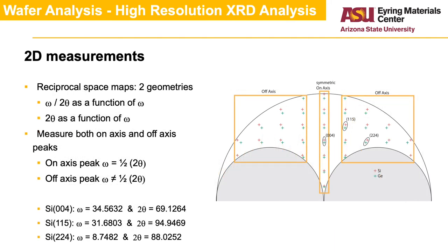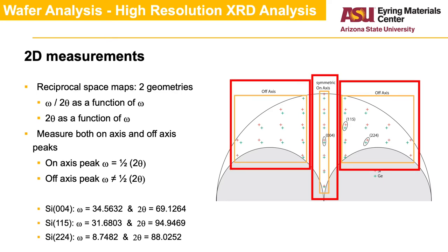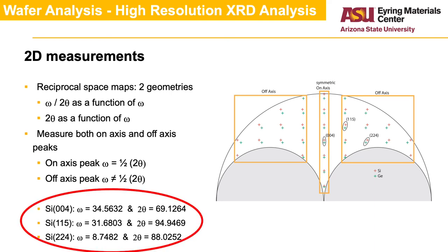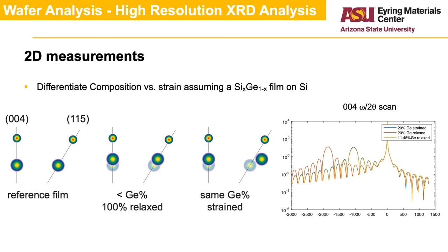The third type of measurement on an epitaxial film is a 2D measurement: a reciprocal space map. Depending on the peak being measured, we can use two types of scan geometry — either omega over 2-theta as a function of omega, or 2-theta as a function of omega. We can measure both on-axis and off-axis diffraction spots since omega and 2-theta are no longer linked. By definition, on-axis peaks have omega at half of 2-theta, and off-axis peaks do not. Once we have completed the measurement, the relative position of the peaks between the film and substrate are key to informing our strain-composition question.